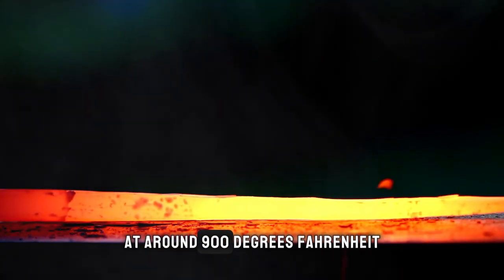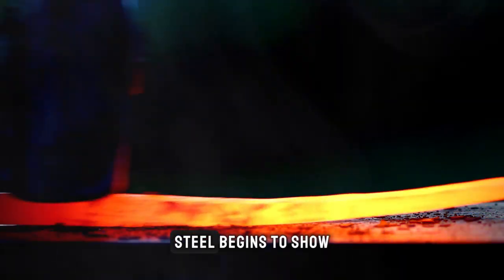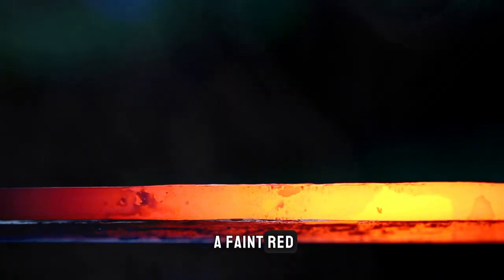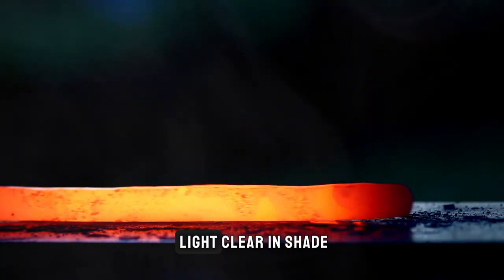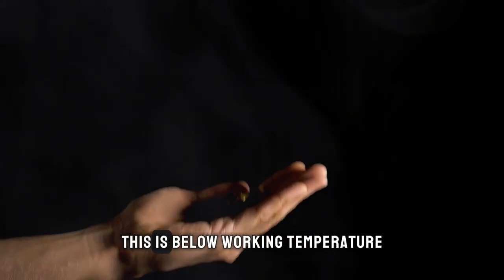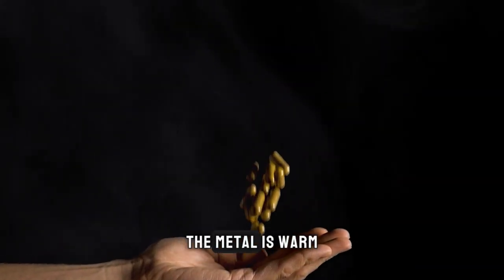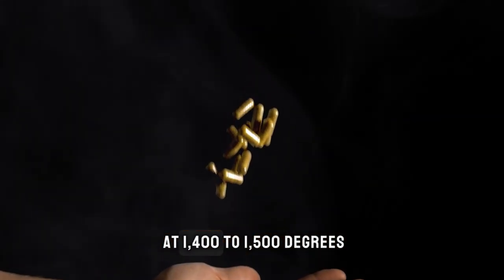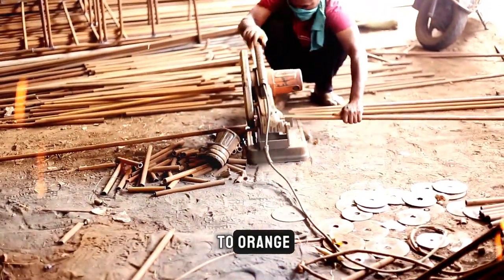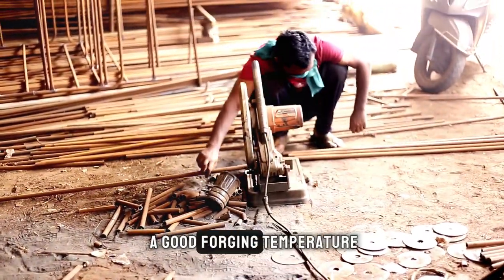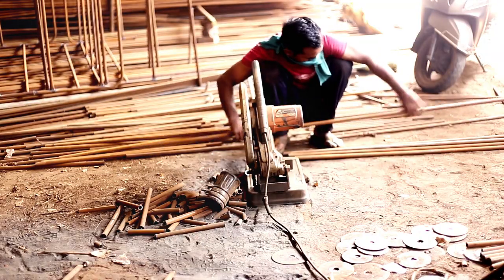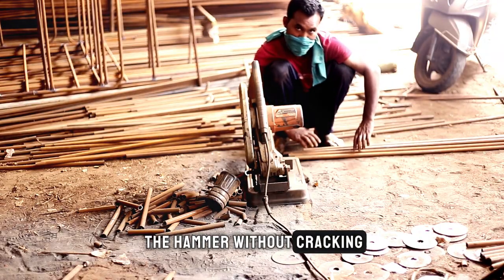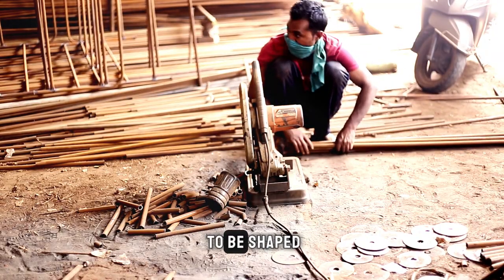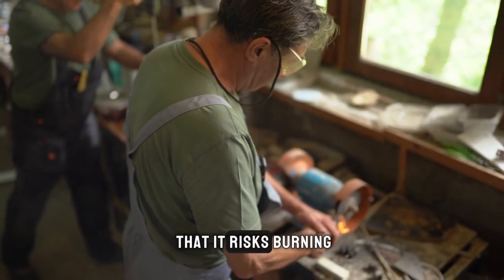At around 900 degrees Fahrenheit, steel begins to show a faint red, barely visible in bright light, clear in shade. This is below working temperature. The metal is warm, but not yet plastic. At 1,400 to 1,500 degrees, a bright cherry red to orange, the steel is at a good forging temperature for most operations. It will move under the hammer without cracking. It is plastic enough to be shaped, but not so hot that it risks burning.